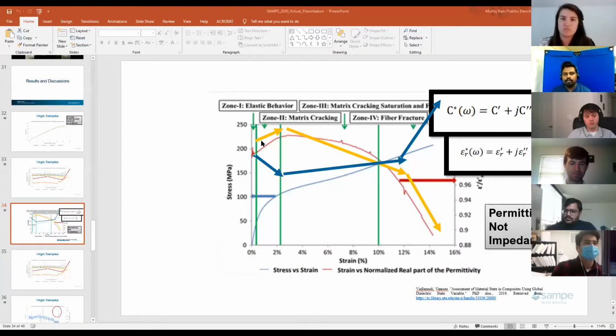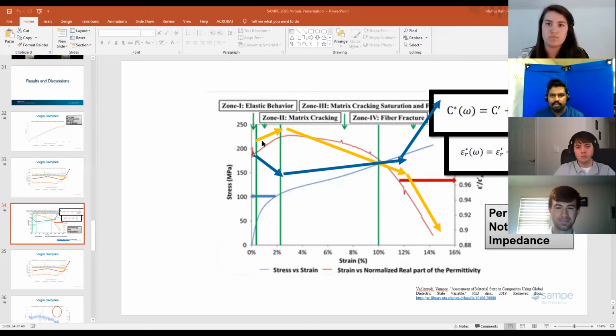Yeah, so I'm just sharing my screen right here. From the literature, what we have so far observed, in this plot, the yellow color curve shows the permittivity curve. For permittivity, what we have observed is that it increases and then has a steady decrease, and it has a final decrease when it ends in failure. And what we expect from the physical relationship for impedance is that it decreases in the beginning and then has a general increase and a rapid increase when it approaches failure.